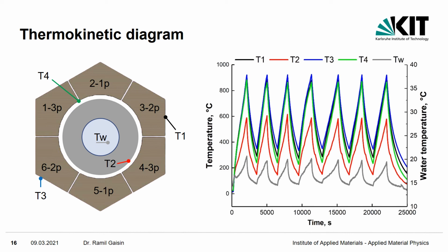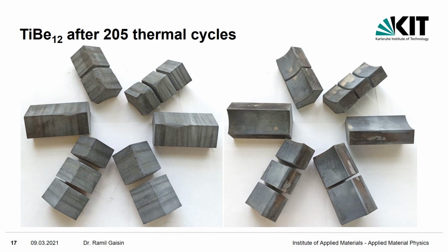And the next slide shows a typical one-day thermokinetic diagram with 7 heating cycles up to 920 degrees and rapid cooling between cycles to about 350 degrees. As a result, titanium beryllide did not fracture and there were no cracks on the surface. This means that the material can withstand at least 205 thermal cycles in rapid heating and cooling conditions. In the next step, we'll improve the setup configuration and increase the number of cycles to thousands.